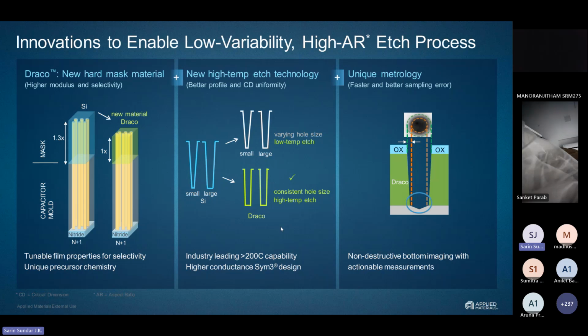This is again with respect to high aspect ratio etch process, but this is typically for 3D NAND. Typically you can see here the nitride layers for N+1 and for the capacitors that are made, SONOS or the process. But here again, defect inspection becomes very, very difficult because some of these aspect ratios come to something like 1 is to more than 500. I think 1 is to 500.